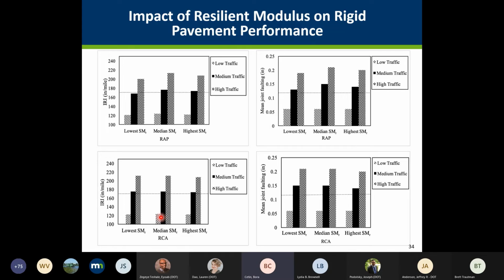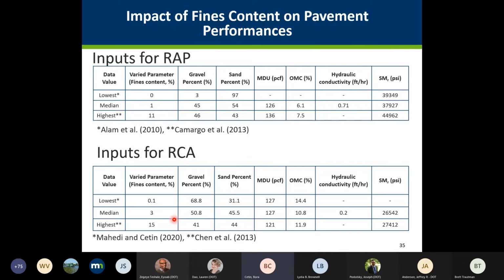And overall, what we see with an increase in resilient modulus value is a slight decrease in the IRI performances under any traffic conditions, but it's not as impactful as it was observed with the flexible pavement performances for both materials. And another set of, like I said, in the report, we show much more refined pavement ME analysis, and I will show another set of figures that show the impacts of fines content on pavement performances.